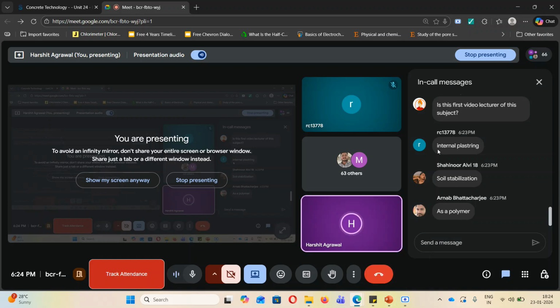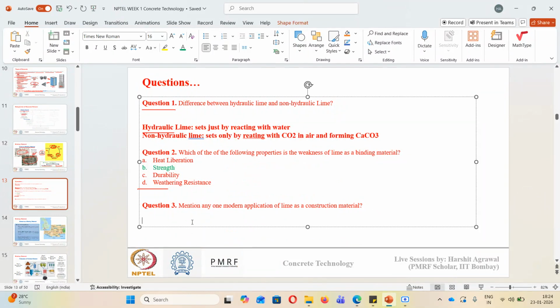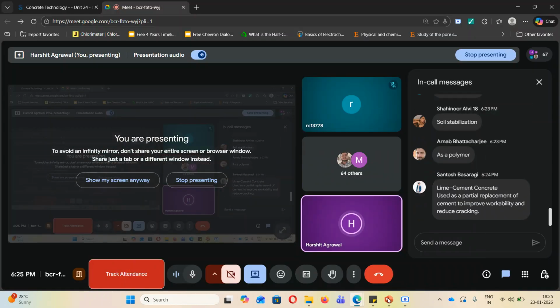Okay, I'm getting answers like internal plastering. Soil stabilization, no. As a polymer, no, it is not used as a polymer. So one modern application of lime is in the repair and restoration of old heritage structures. Heritage structures were originally made with lime mortar. Now for repair of those structures we need a material which is compatible with the material that was originally used, and that's why, for compatibility with historic materials, we use lime till date for repair and restoration purposes.